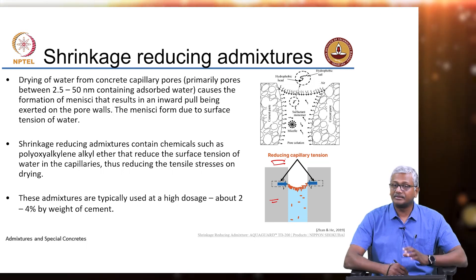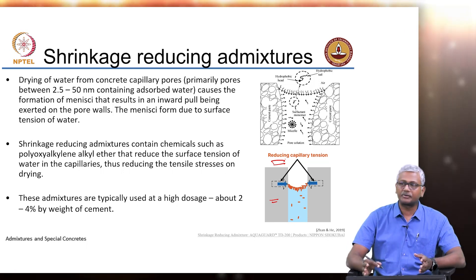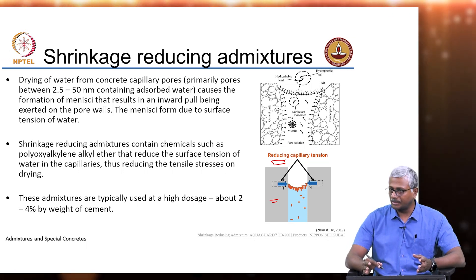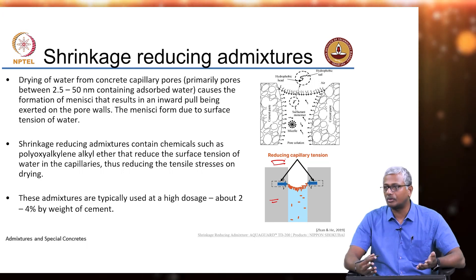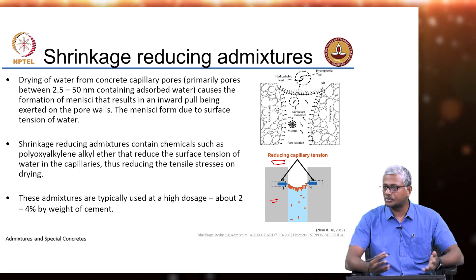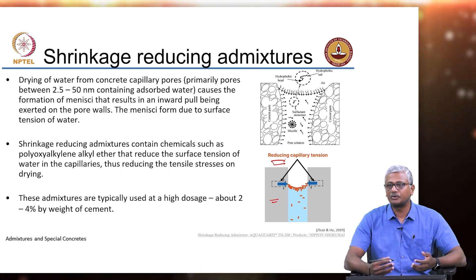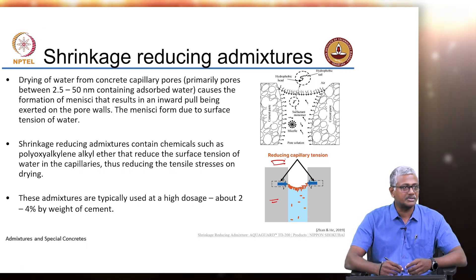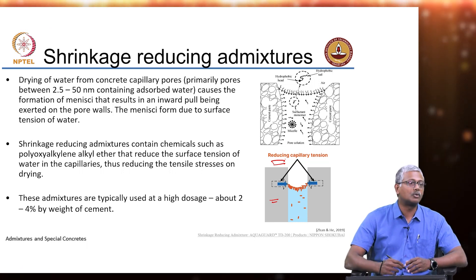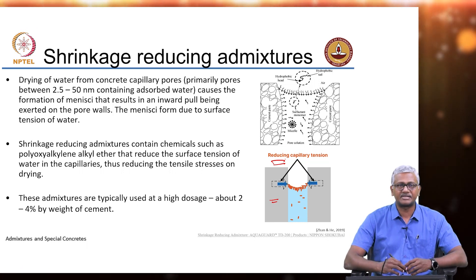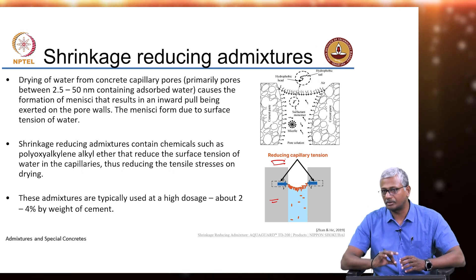These chemicals need to be present throughout the microstructure of your concrete — entirely in all your pores — to actually have a much more uniform effect. That is why we use very high dosages of 2 to 4 percent, which makes the overall application of these admixtures quite expensive in concrete.